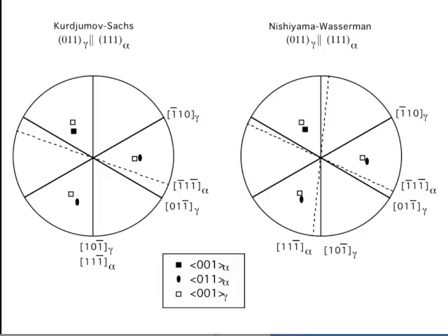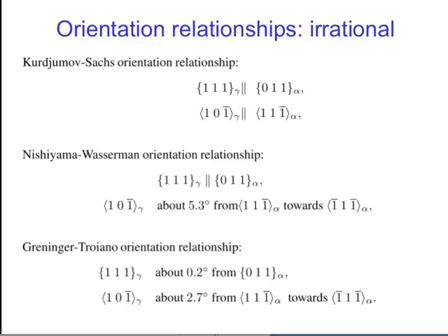And if we look at the orientation relationship between the austenite and the martensite, then you'll find that the close-packed planes of the two phases are approximately parallel, but they might be inclined at 0.51 of a degree, but they are not exactly parallel, okay? And the close-packed directions in those planes are approximately parallel as well, and that's given in your notes, I think.